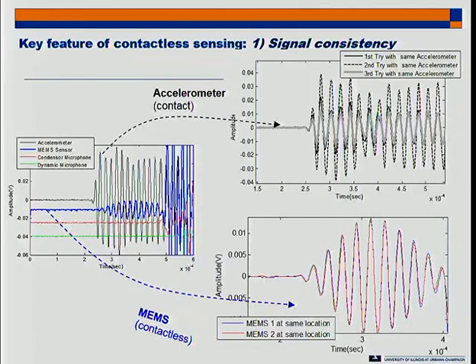But with MEMS, we have great consistency because we don't have that coupling problem. You put the sensor there, put it back again in the same place, we get the same signal. It's very consistent. So that opens up a whole new avenue of characterization, and that is, can we use the amplitude now? Now that we've gotten rid of this problem, we'll use amplitude to see if we can characterize the material. And I'll show you some results where we use amplitude to do that. We can only do that because it's air coupled.